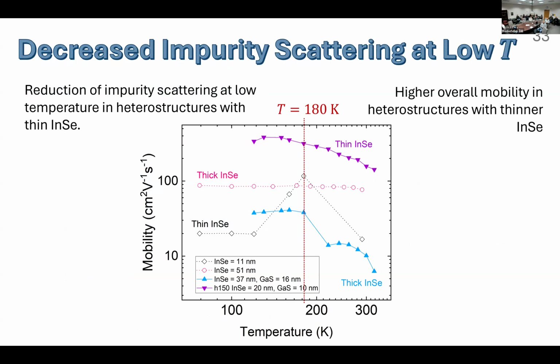Another thing that points towards the importance of the role of thickness in our device parameters is looking at the mobility as a function of temperature for a series of different heterostructures as well as bare indium selenide flakes. For example, the curve with the diamond in black is a thin indium selenide flake. At temperatures below 180 degrees Kelvin, we see the presence of impurity scattering. This is seen as a positive power law dependence, whereas for thicker indium selenide, this is absent.